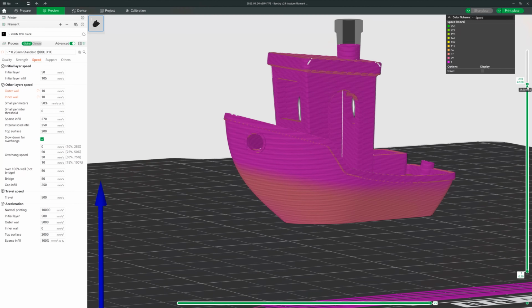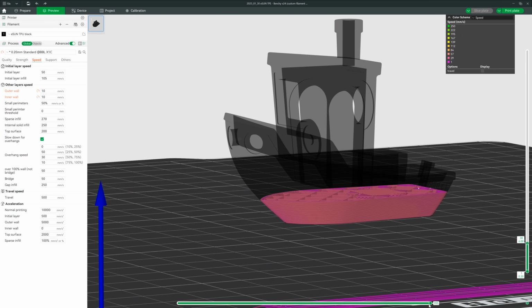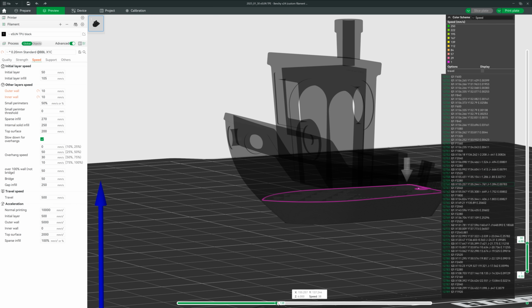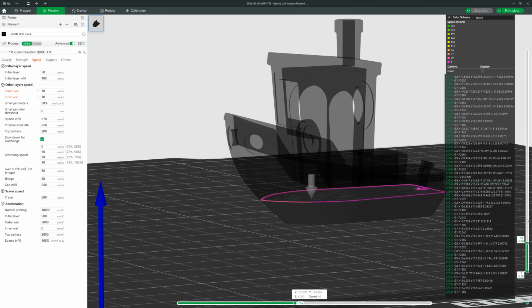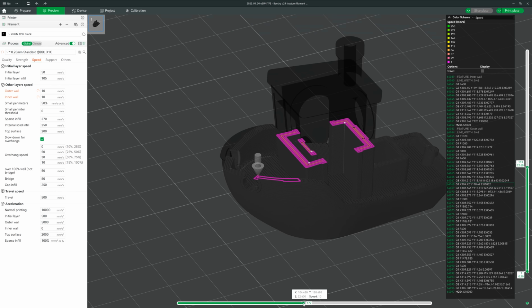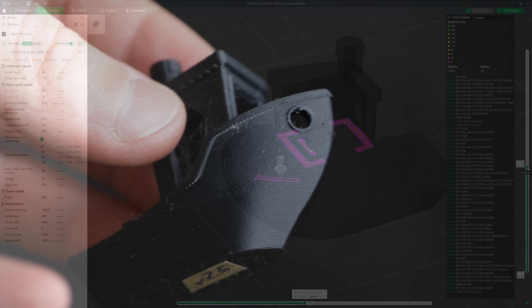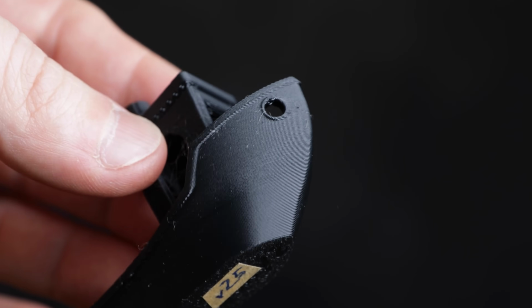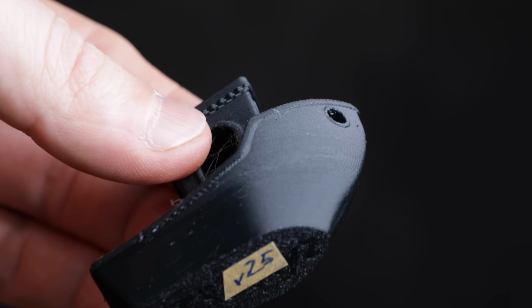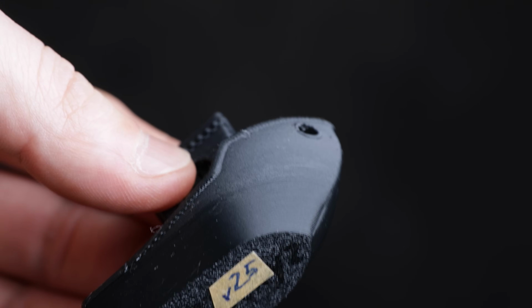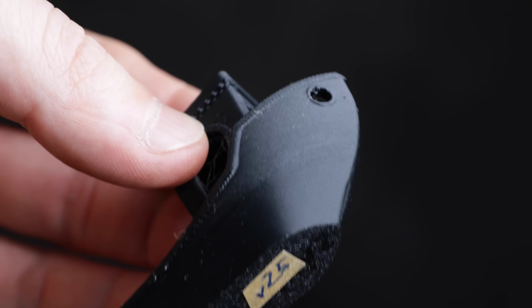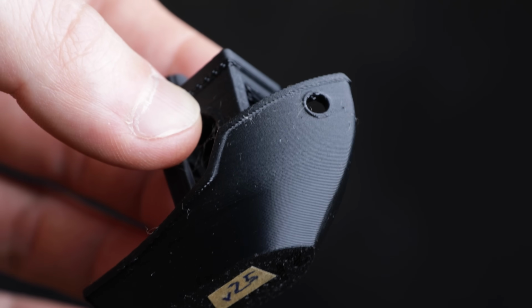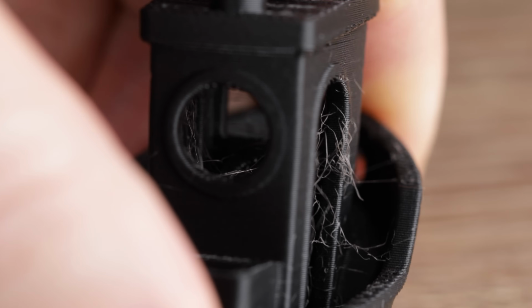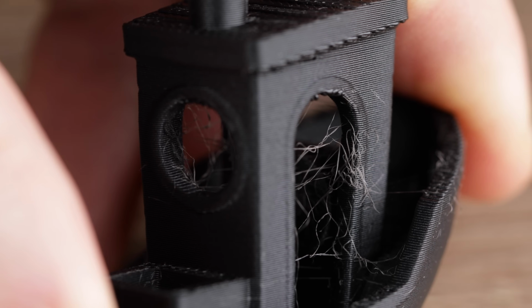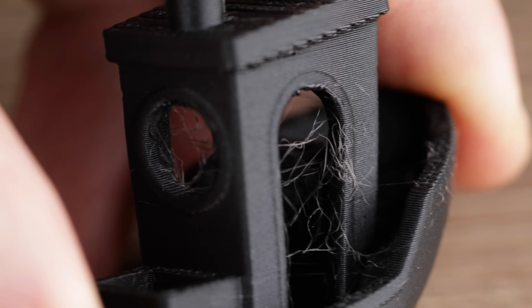Why? Checking the speed scheme in the slicer reveals the answer. The lower region was printed at 30 mm per second, the upper region was printed at 10 mm per second. And that's fascinating, because now we know for sure that we can control the surface finish by adjusting the print speed. If you want the matte finish, print slowly with 10 mm per second. If you don't care, you can print faster. And last but not least, then we have stringing in the cabin area. Where did that come from?